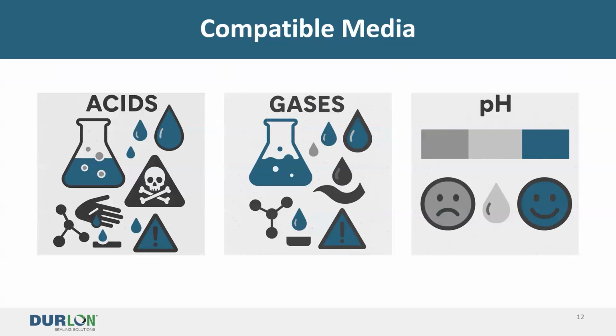And then the pH. When you have a range, we say it's 0 to 14, which is the full spectrum. But there are applications, and I mentioned it a little bit earlier, particularly about CIP type cleaning in the food and beverage industries, where they will do a wash with something that is very acidic, and then they will come back and hit it with a very caustic material. So you see a very low pH on one side, and then they will bring it back the other way to make sure that they've cleaned the system well and killed off any bacteria, et cetera. So that is an application where, paired up with stainless bolts and whatnot, a low stress gasket with resistance to a wide range of pH and aggressive chemicals would be a very good fit.